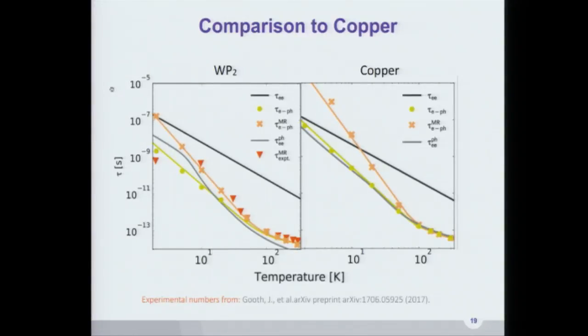What's the shape of the sample? So these are needle-like, and they do different kinds of transport measurements. And the lifetime measurements were done by Johannes Gooth and Claudia Felser's group. And how does the surface versus the bulk matter? Because cyclotron orbits do this kind of thing on the surfaces. That's right. For these same lifetimes, we don't see that much of a difference between the surface only and the surface and the bulk lifetimes. When they're measuring them, they're seeing a convolution from the two, so it's not something that they're able to completely separate out.